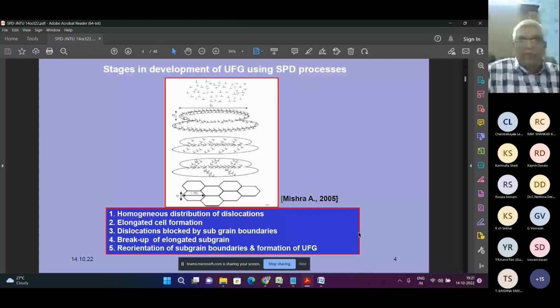In step one, you can see the homogeneous distribution of dislocations. Whenever any material, suppose titanium or aluminum or magnesium or steel, is under normal condition, you have a lot of dislocations, a homogeneous distribution of dislocations. Whenever you want to process or deform it, these dislocations move. What is meant by dislocation? They are supposed to be in one position, but due to this deformation, they change from one place to another place.